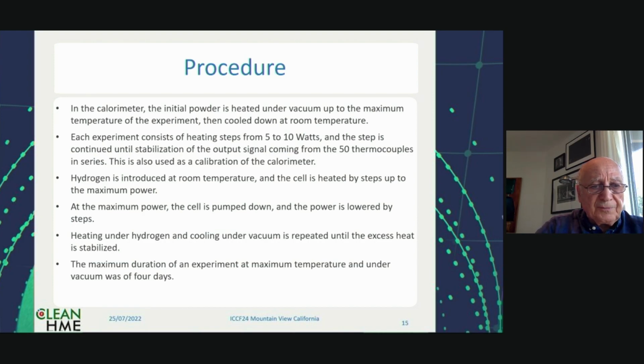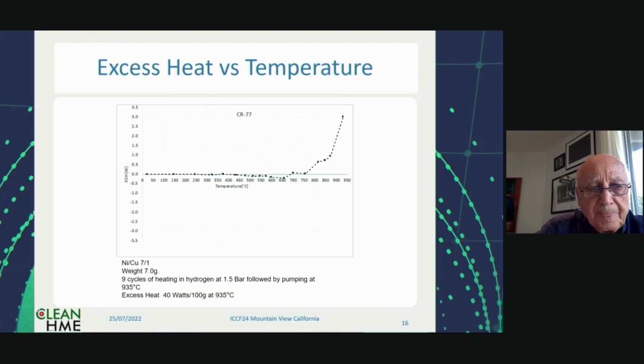The maximum duration of an experiment is about 4 days. Okay, next slide, please. Okay, this is an example. This is the final state, when we have stabilized everything. We do the heating, cooling, heating, cooling, heating, cooling with hydrogen and vacuum, hydrogen and vacuum. This is a nickel-copper ratio of 7:1. The weight was 7 grams, and 9 cycles were done under hydrogen. Next slide, please.